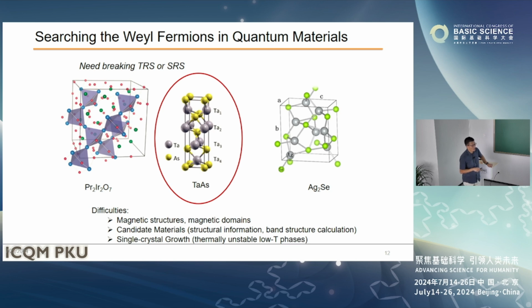Many compounds we tried like 7 or 10 years ago. But many compounds have some problem in the experiment. One is that the structure information is not correct, or the band structure calculation is not precise, or some compound is difficult to form a single crystal. Like this one, it has a low temperature phase which breaks inversion symmetry. The high temperature phase is a high symmetry structure. So if you cool down to a low temperature, usually you cannot obtain the low temperature phase. So this is difficult and very annoying.